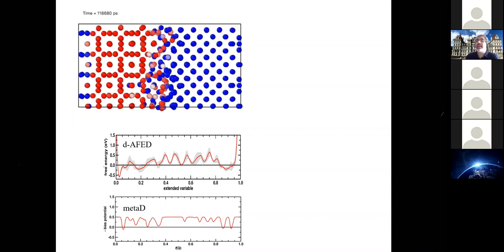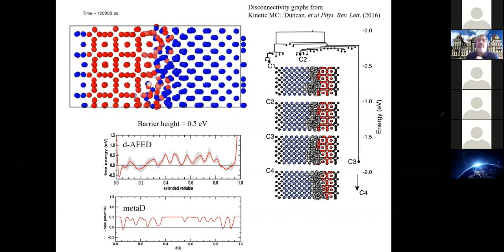And in fact, you can compare this number to kinetic Monte Carlo studies that have been done previously. And in kinetic Monte Carlo, the idea is to get the right barriers out. And you can see from this disconnectivity diagram that each layer transition costs you about 0.5 eV. So now we're seeing this as a way to get polymorphic transitions that actually carry kinetic information with them. All right, we've done this for the atomic crystals, but we think we can also take this over into the realm of molecular crystals.